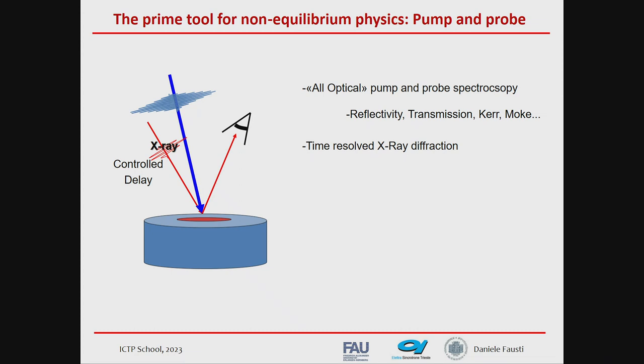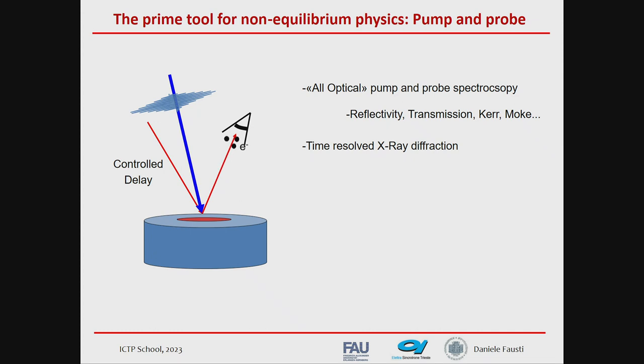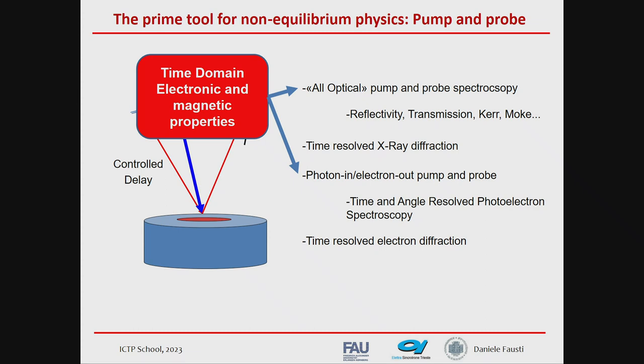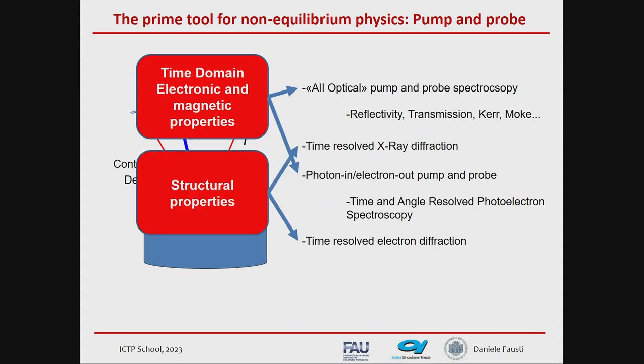You can also use the pump-and-probe concept where photoexcitation is used but the observable is not photons but electrons out — that's called time- and angle-resolved photoelectron spectroscopy, which tells you the electronic states in the material. You can even use bunches of electrons to measure time-resolved electron diffraction. On a sub-picosecond timescale you can measure most electronic properties available at equilibrium, and also structural dynamics via X-ray and electron diffraction or microscopic imaging.